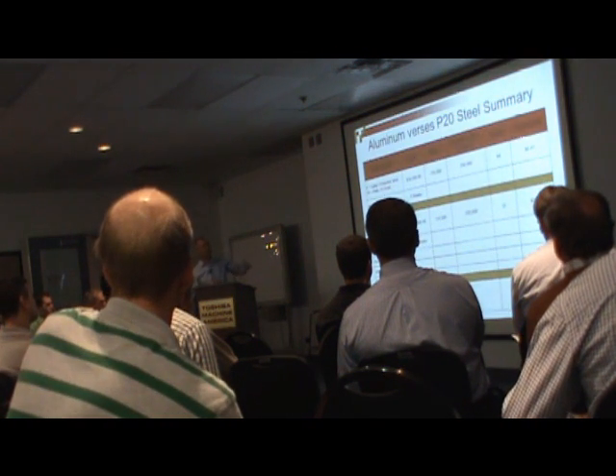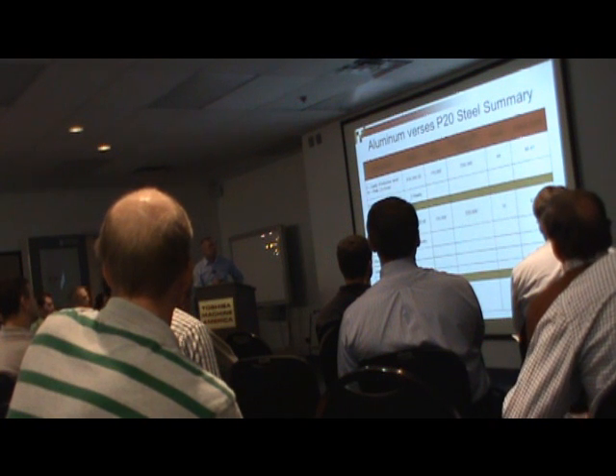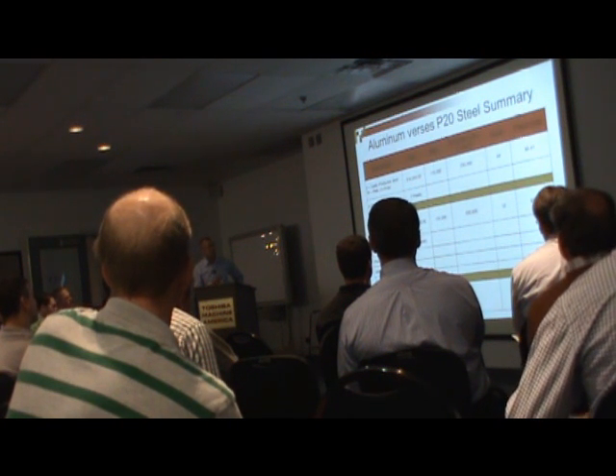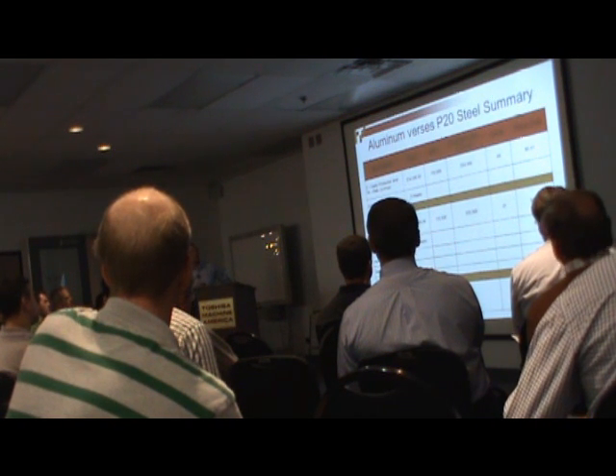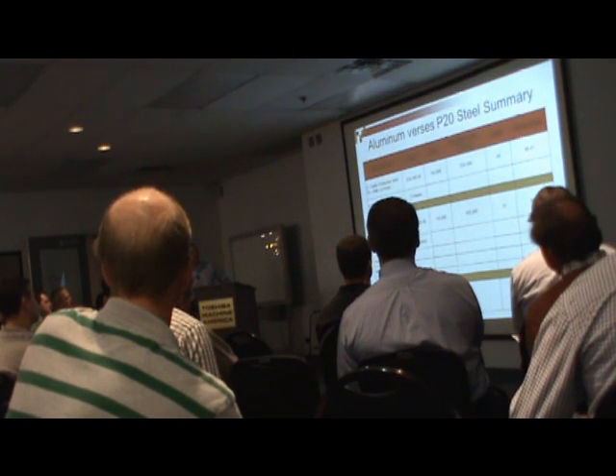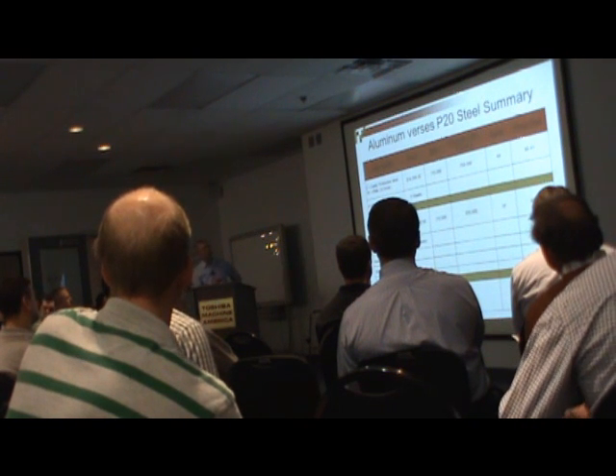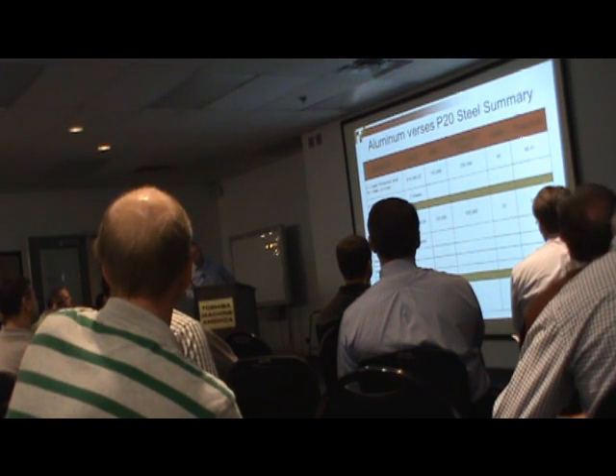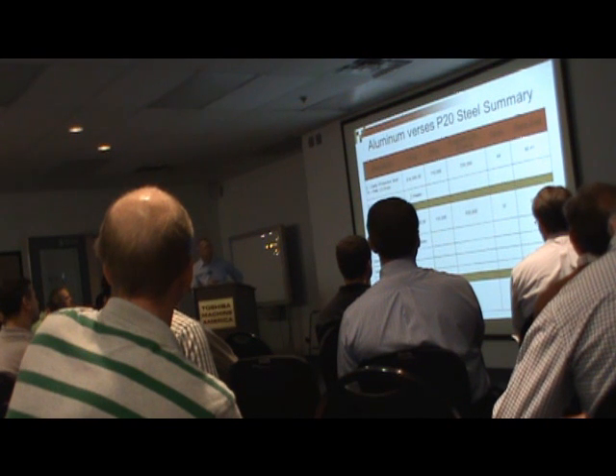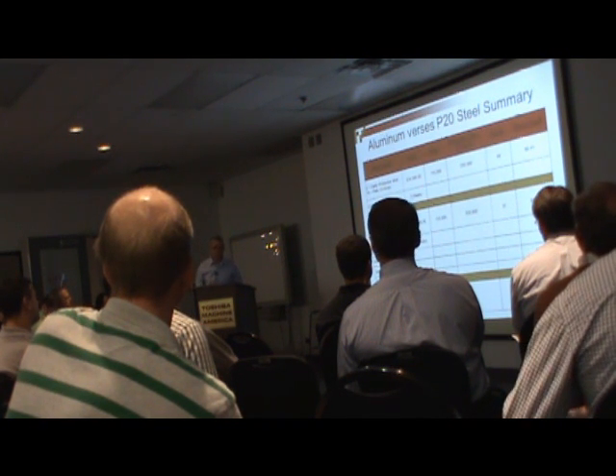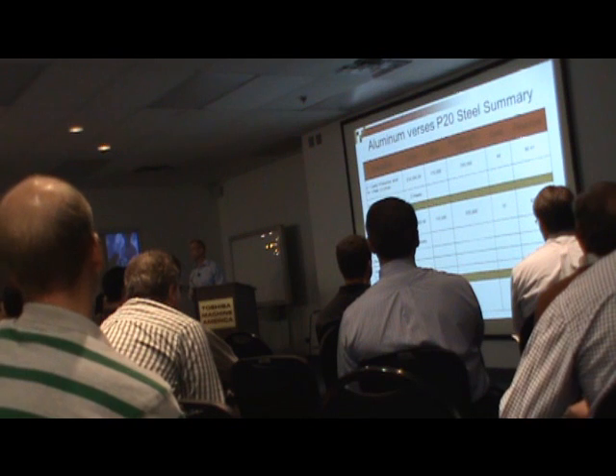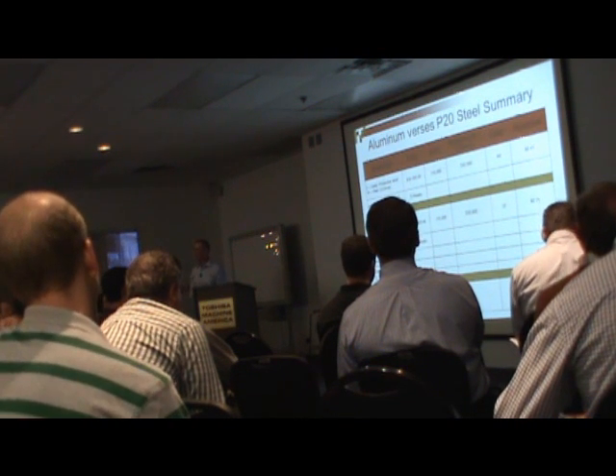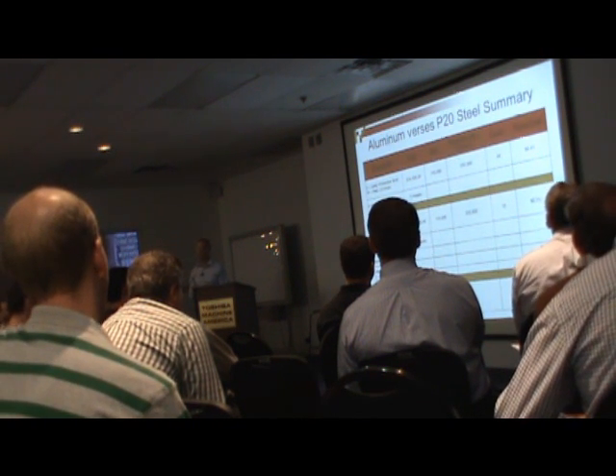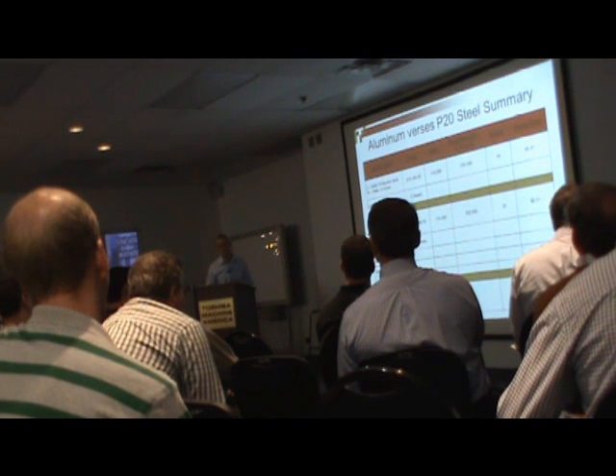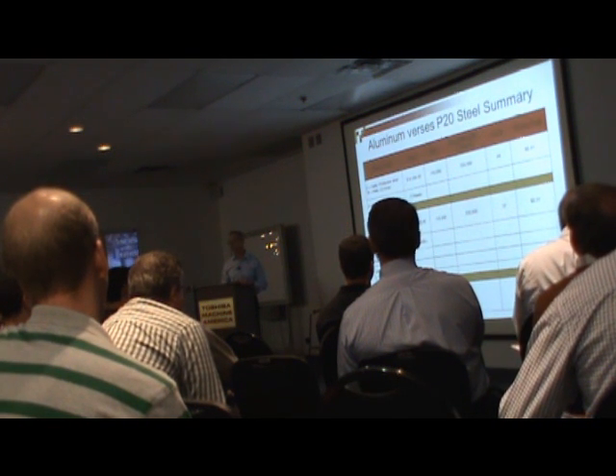The case study summary, just to give you an idea, there was only about a $12,000 cost savings between a P20 tool that they had built that was done in 5 weeks, and ours was $22,000. So it was only very little cost savings. When you run this out over 5 years at 110,000, it equates to only, what, $55,000. Total savings was only $67,000, but look, that's one part, and that was a low volume, and that was only a 2-cavity. Multiply that by, if you're running 100 different tools for a customer, what that could turn out to be.